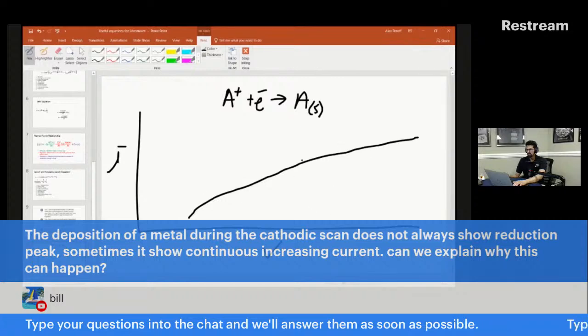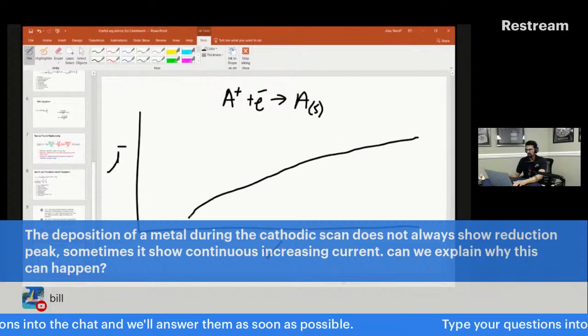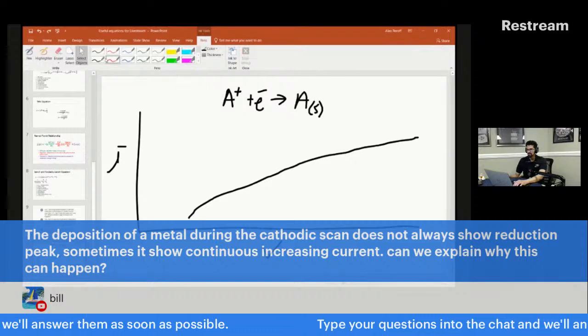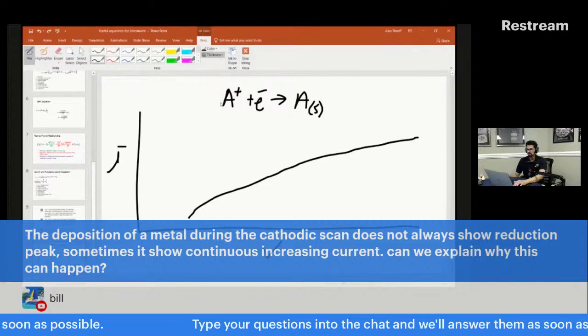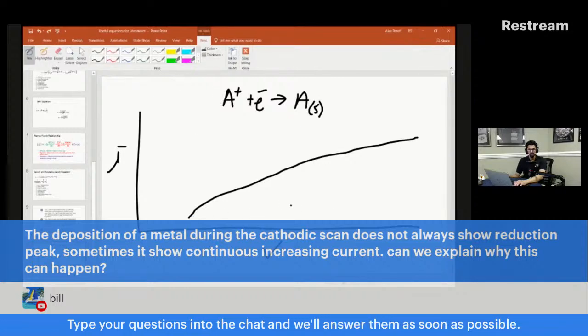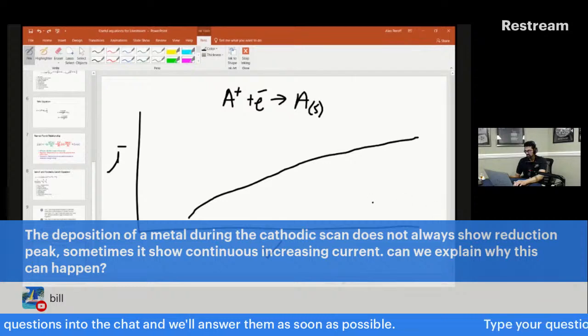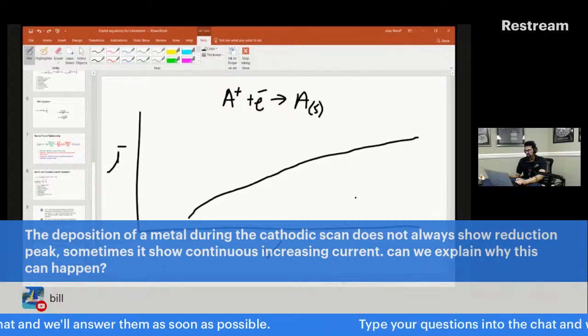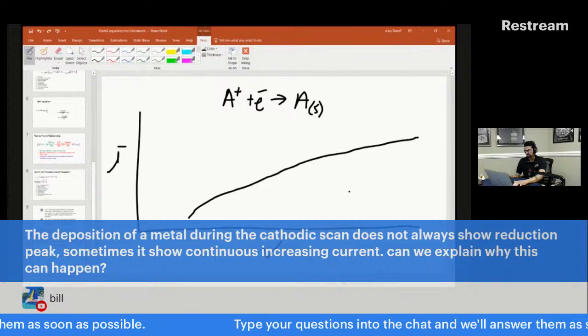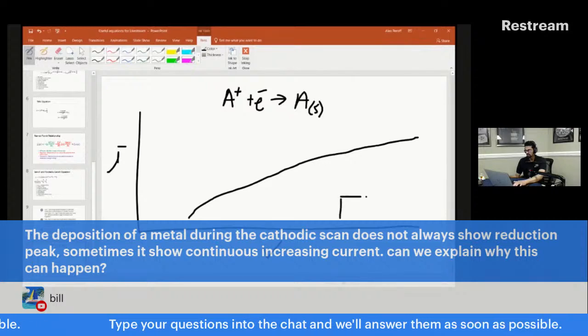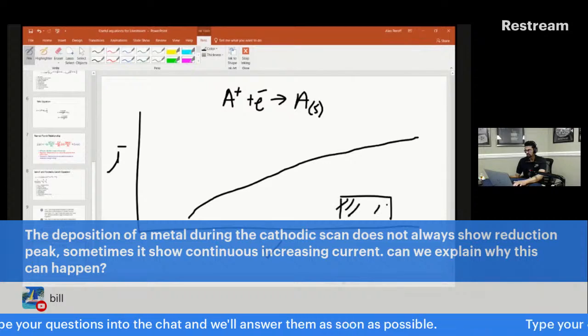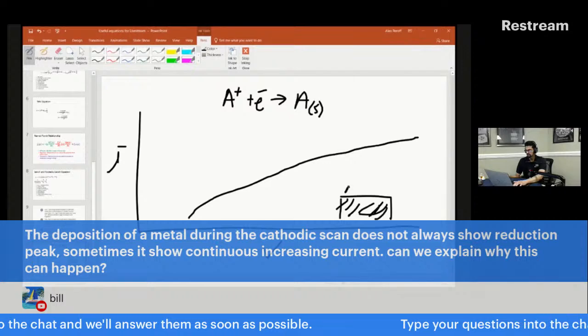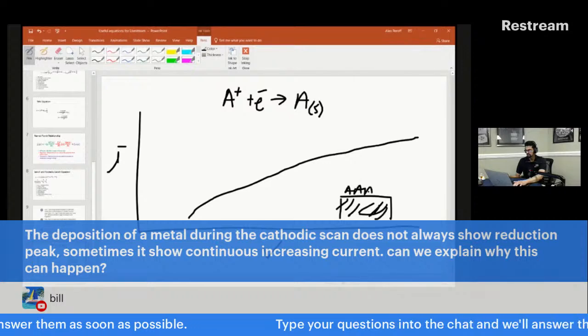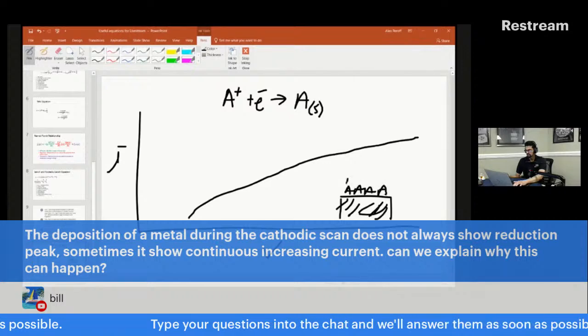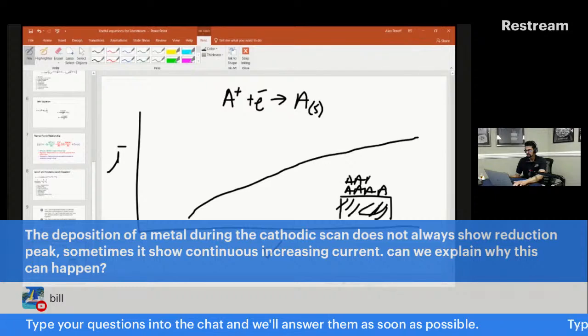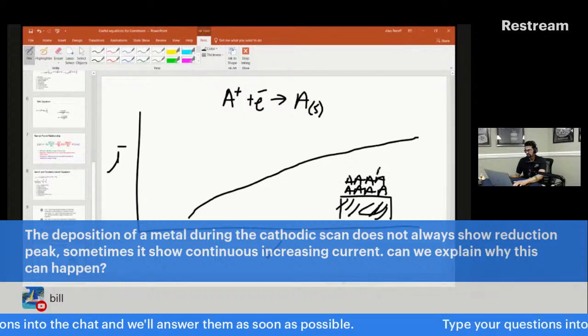If you keep having layers and layers on top of it, you never get this peak, right? That's probably because it depends on the voltage range, which is going to be part of it. There actually may be several things happening in this situation, but you have some kind of bare surface, and then you have a row of A's generating, and then you continue to have A's plating on the surface.